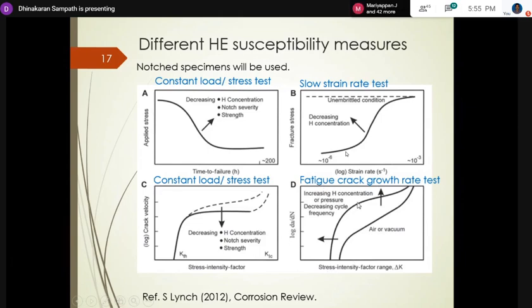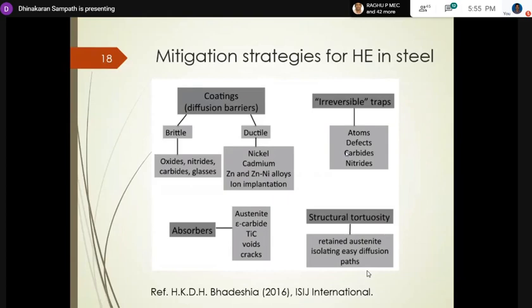Fatigue crack growth rate test. Again, this is crack growth rate as a function of stress intensity factor range. It's a range because it's the difference between the max and min of that sinusoidal wave. So this is the crack growth rate, the typical sigmoidal curve in air. And in the presence of hydrogen, it goes up by several orders of magnitude. The crack growth rate increases throughout the entire regime, including threshold and the Paris region. This is also expected to be more or less the same, but I think they show it like that. So those are the testing and susceptibility measures.